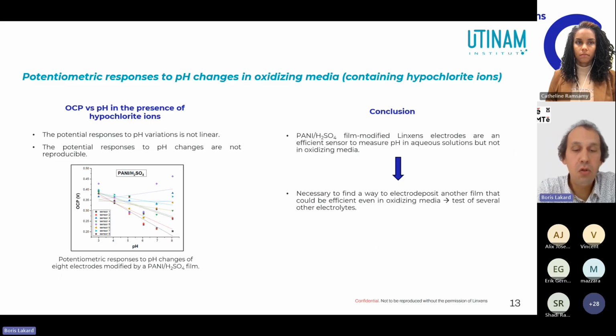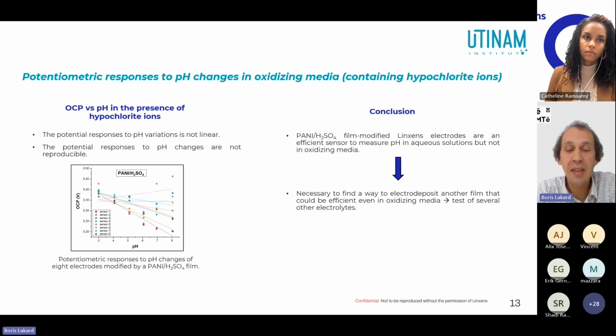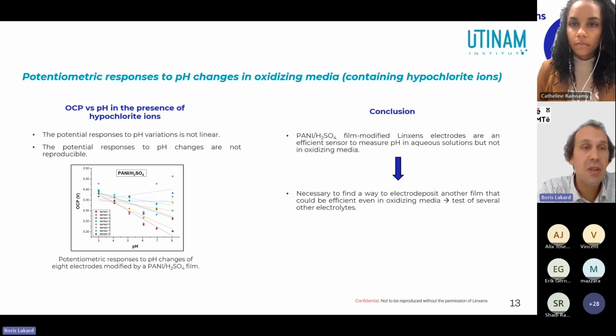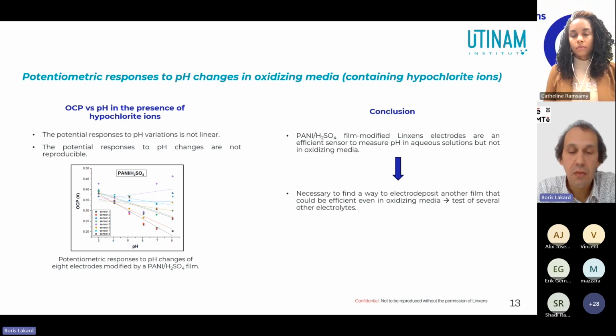We then wanted to use the same sensors with the same polyaniline film to make similar measurements in a medium containing hypochlorite ions, but the results were disappointing as the variation in potential as a function of pH was no longer linear, as you can see in this figure. So we had to find another solution.